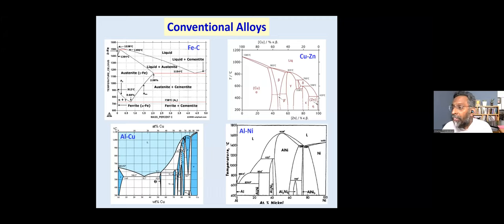So why is that so? The moment you add more than that, the steel becomes so brittle that you cannot make a good component which is usable. The same is true with copper zinc alloys. In brasses, up to about 30% of zinc in copper is usually common. If I add 50% zinc in this alloy, the alloy becomes so brittle that you cannot use it as a structural alloy, a structural material.